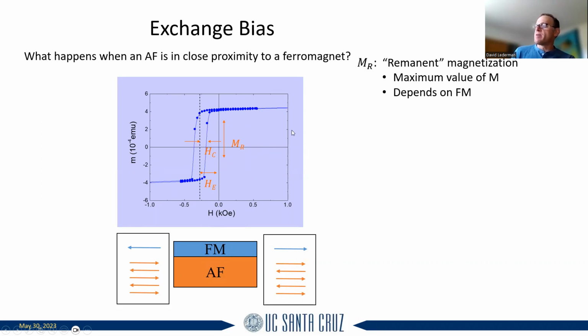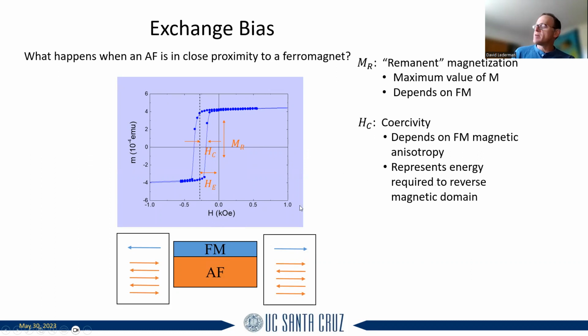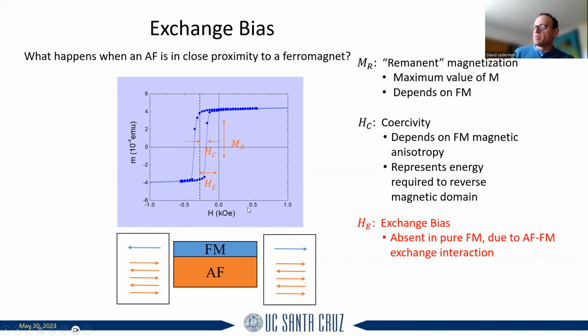Okay, so here you have the remanent magnetization, which is this right here. I'm just trying to also show you some terminology that I'm going to use. This is the coercivity of the loop, the width of the hysteresis loop here. And then importantly is the exchange bias, which is the shift of the entire loop away from H equal to 0. This is absent when you have a pure ferromagnet, and it's due to the antiferromagnetic-ferromagnetic exchange interaction right at the interface. So this is an interface effect on the exchange interaction between the ferromagnet and the antiferromagnet. It acts like an external field that you cannot, in principle, reverse. Okay,